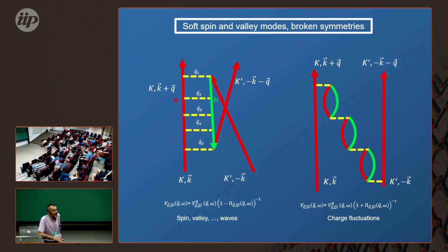No, not at all. What I'm saying is that the long-range interaction is enough to describe the main trends for a variety of twisted and untwisted systems. For me, the most striking result is the fact that a twisted bilayer is one thing, a single layer on top of a bilayer is totally different with respect to superconductivity. I'm not sure, because all these systems, a double bilayer, one layer twisted, they also have so-called insulating phases, but they are not good superconductors at all. And it is related to the strong Hartree deformations which are specific of a bilayer or a symmetric trilayer or a symmetric four-layer system and so on. So the twisted bilayer stands out because of these strong deformations of the bands.